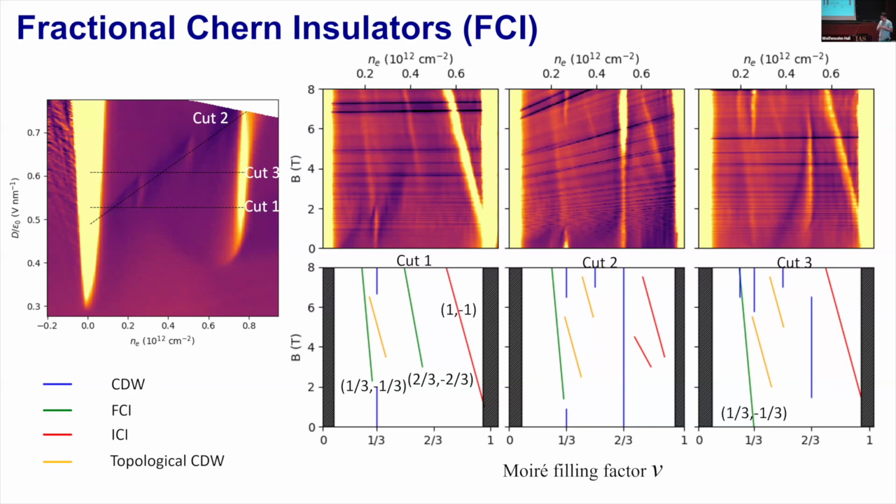Regarding the twist angle inhomogeneity, there must be twist angle inhomogeneity in any Moiré. But the fact that this Moiré is a hetero-bilayer Moiré makes it much more robust against twist angle variation, because the period is mostly set by the lattice mismatch. So it's there, but it's probably a much smaller effect than in the homobilayer TMD or graphene. Yeah.